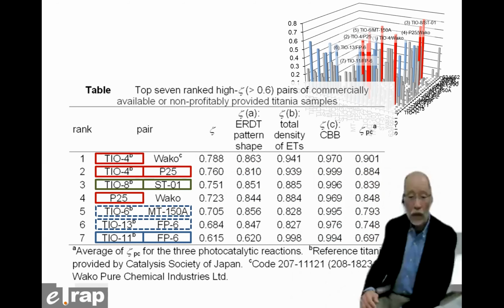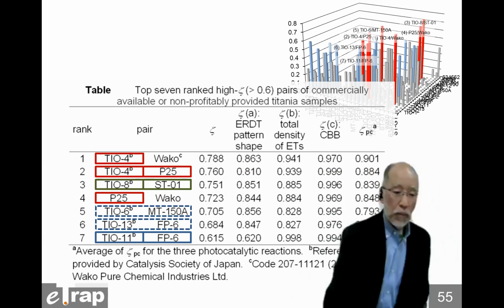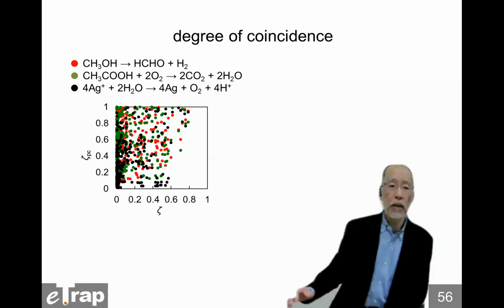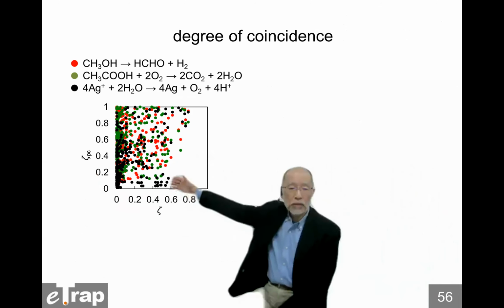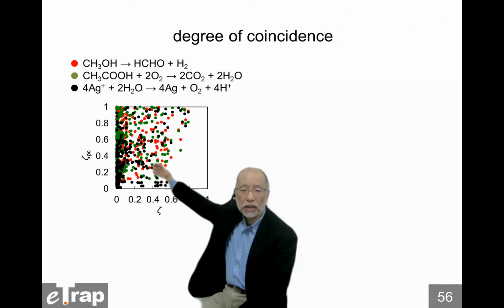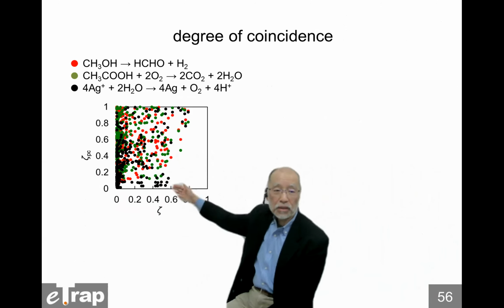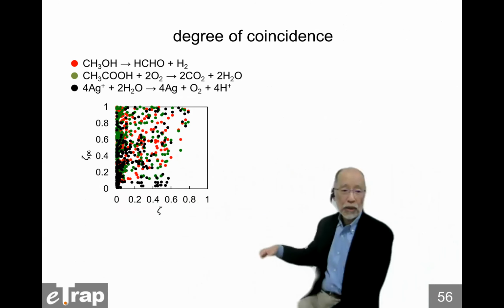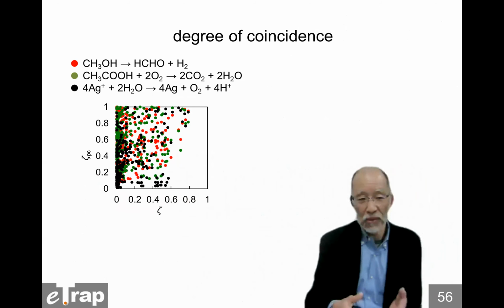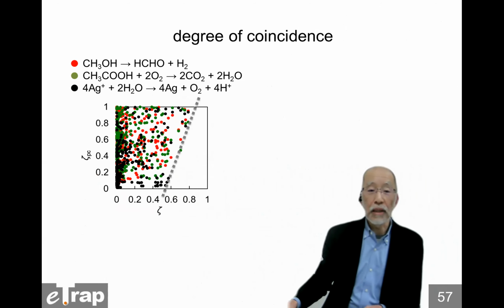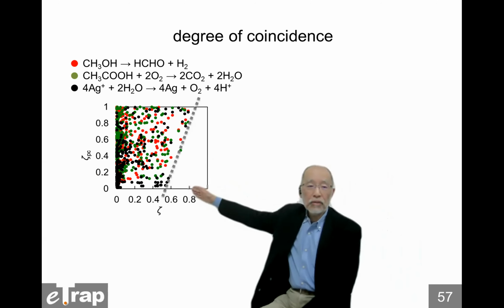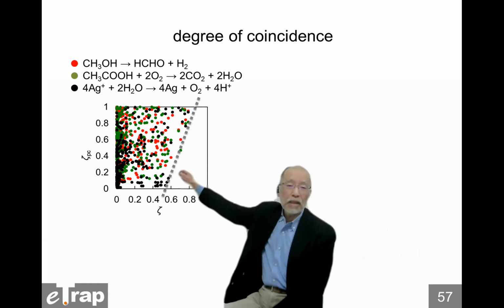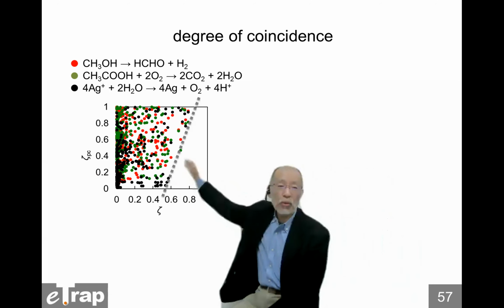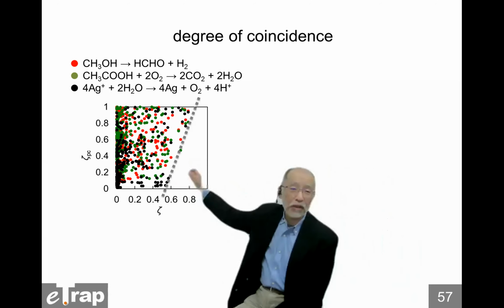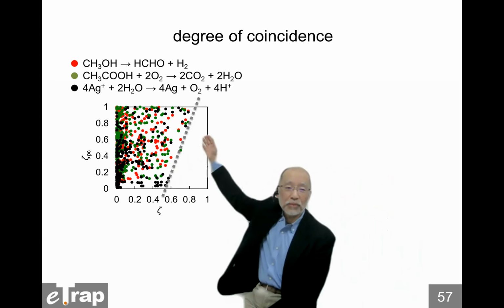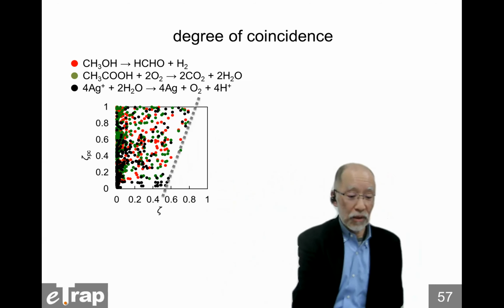To make it clear, the zeta PC, the degree of coincidence of photocatalytic activity, is plotted against the zeta value. And there is almost no relation. But here is a line. So high degree of coincidence pairs don't give a low degree of coincidence of photocatalytic activity. That is, similar samples give similar photocatalytic activity.